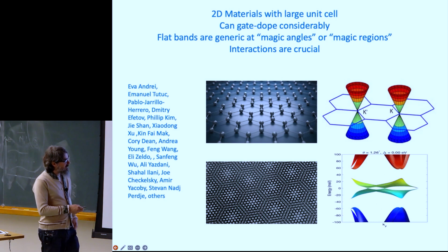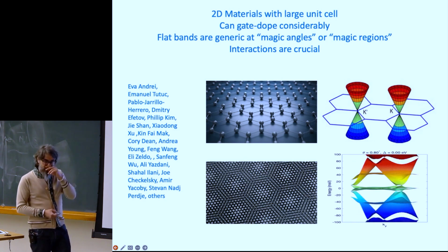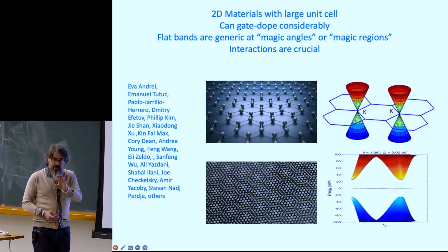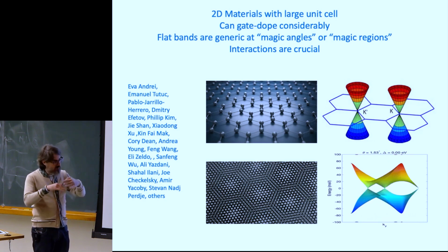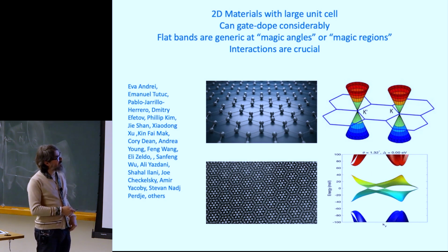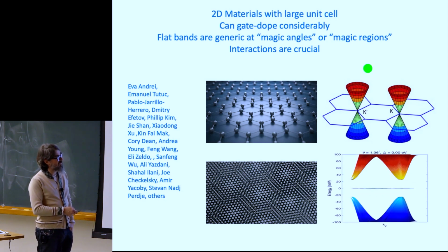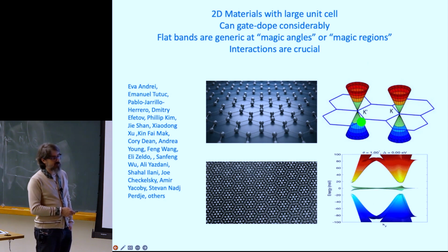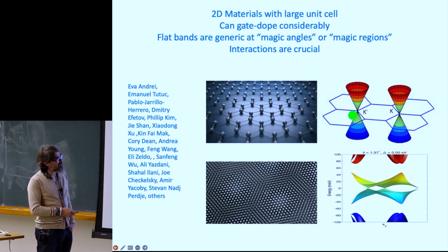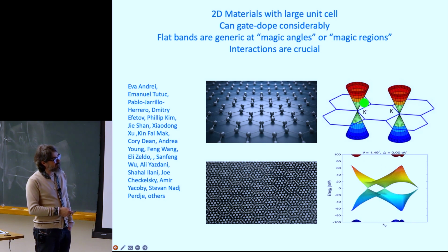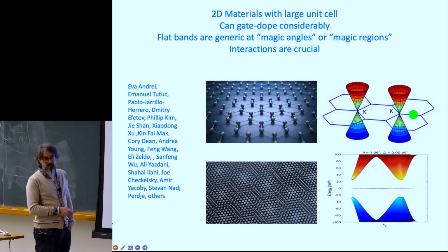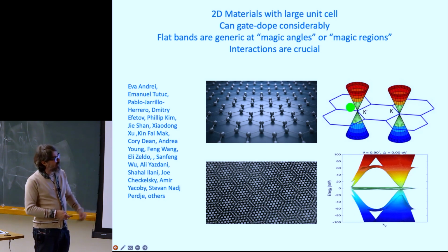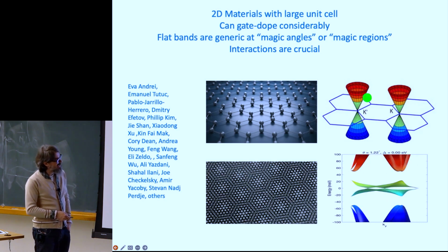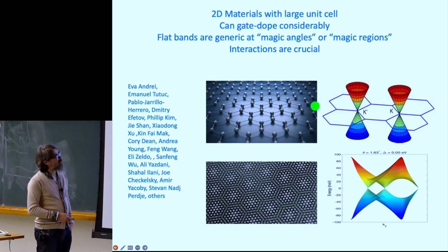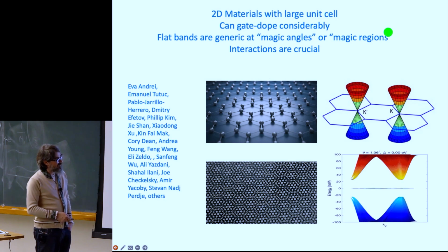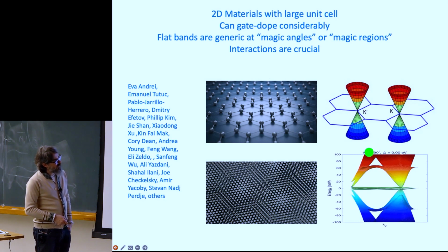Now, in single layer graphene, people have been trying to induce interactions without a magnetic field. If you add the magnetic field, the bands become flat, Landau levels, other physics. But without a magnetic field, people have been trying to observe interacting effects, and there are none. The reason for this is the low density of states of a Dirac electron, which is 0, because exactly at the touching point, I have 2 states, really. So 0 in the thermodynamic limit when you divide by the area.